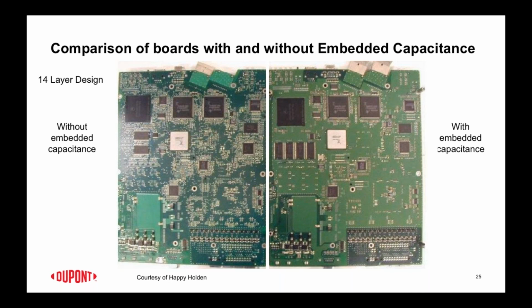And where do you typically put your decoupling caps? You put them around your ICs, around your packages, because you want to have the lowest inductive loop. That's usually the most valuable real estate, because that's where your highest routing density is. So by removing these discrete capacitors, even though they're getting very tiny, they still have vias and connections, and they still take up some amount of real estate. So you can clearly clean up the board by using embedded capacitance.